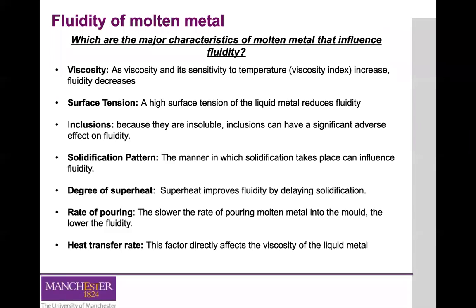The solidification pattern — the manner in which solidification takes place — affects the fluidity of your material. Fluidity is inversely proportional to the freezing range or solidification range. The shorter the range, as in pure metals, the higher the fluidity. In the case of alloys, the longer the freezing range — or the higher the difference between the solidus and liquidus temperature — the lower will be the fluidity and the more difficult it will be to fill in the mold cavity.